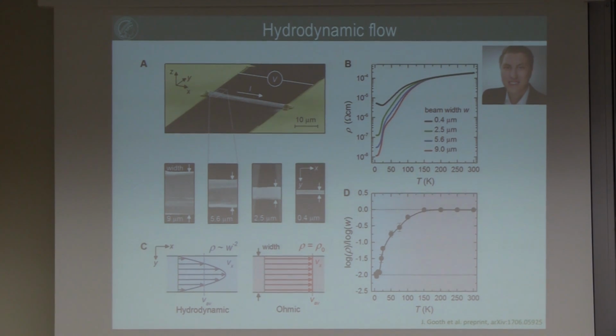So niobium phosphide, if you make it micrometer smaller than the mean free path, and the mean free path in this material is very large, you see a dependence on the width. If you look how the resistivity behaves with the width of the single crystal, there's nothing happening in this area, so it's still Drude behavior, no width dependence. This is a ballistic width dependence, going with 1, and this is a hydrodynamic width dependence.